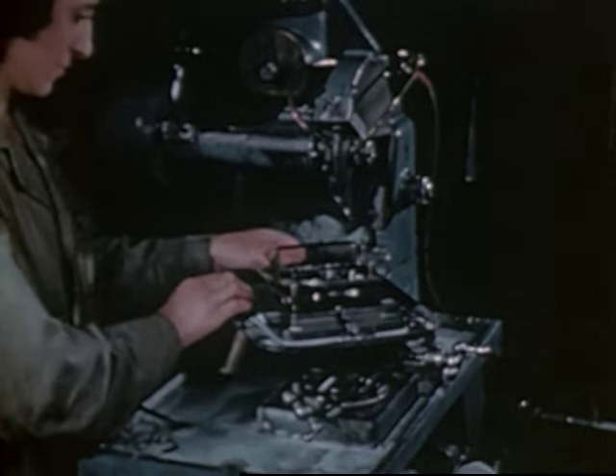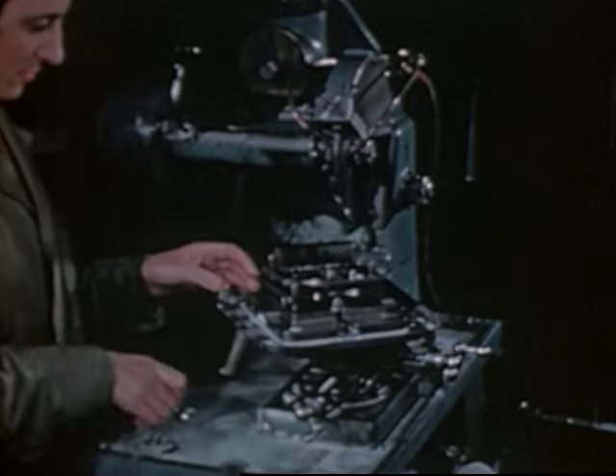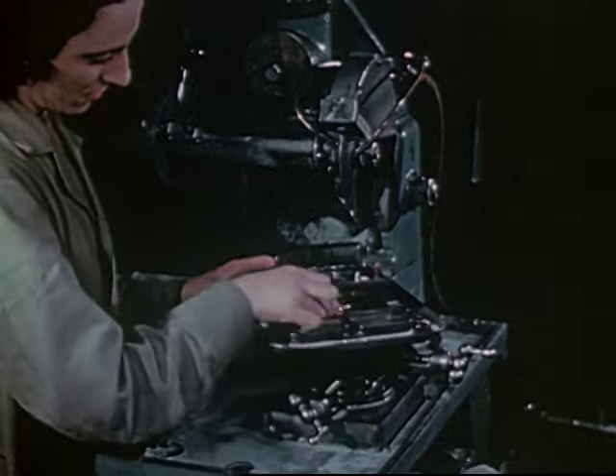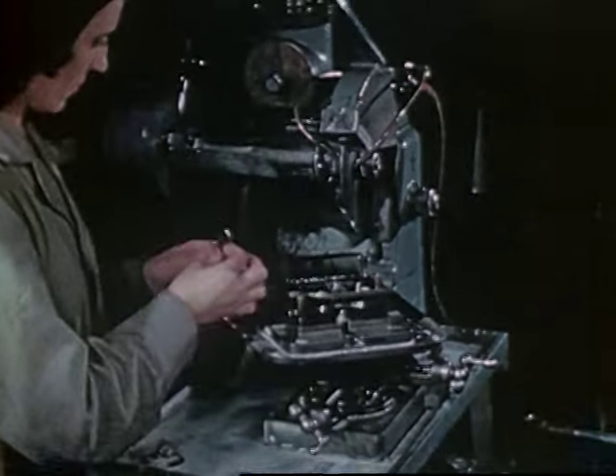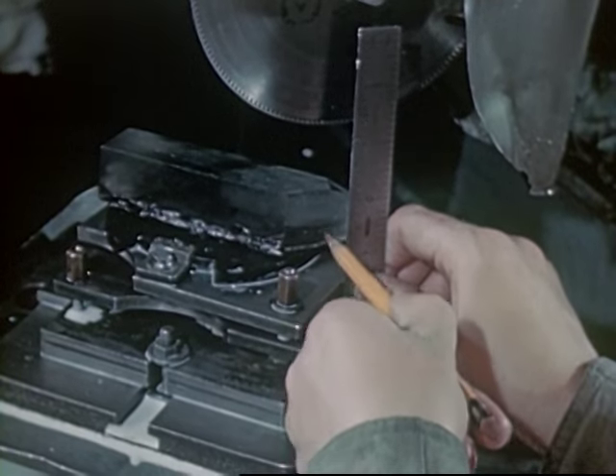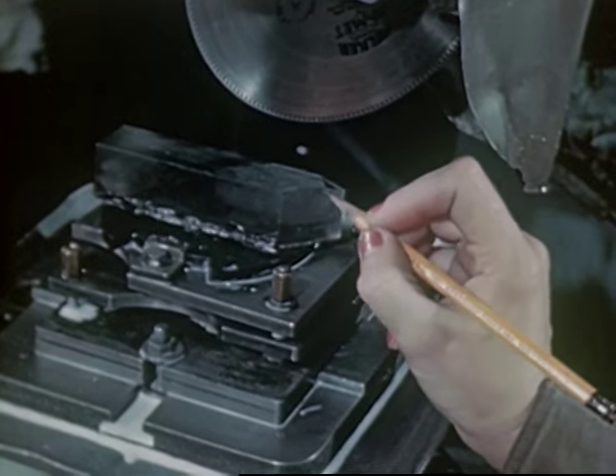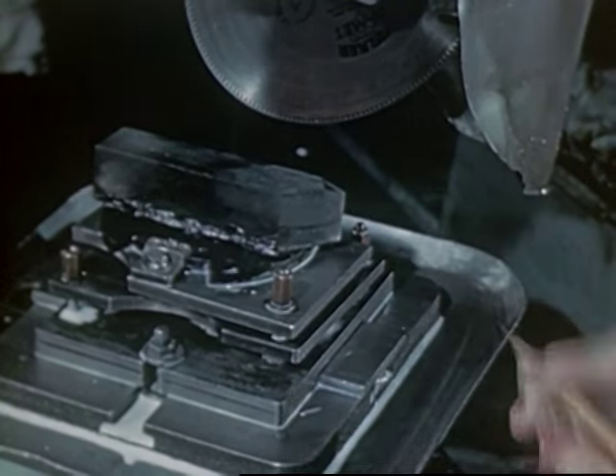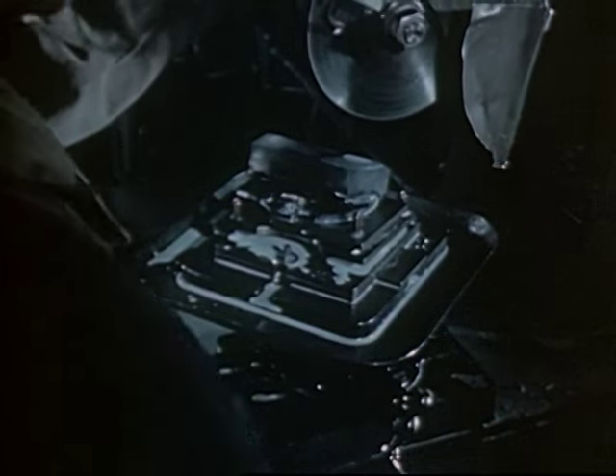Vertical arrows have been drawn on the quartz in two previous operations so that the crystal would not get inverted. After the jig is firmly bolted to the saw head, a preliminary cut is made to remove the end of the bar. And again, an identifying arrow is drawn to keep track of the up direction of the first wafer to be cut. The rough wafers are rarely more than a 1/16 of an inch thick, and it is quite an art to saw them thin and true from this hard and brittle material.